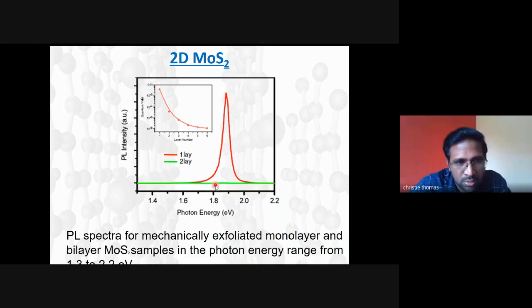Okay, and also in the inset, I think it's not clear. The y-axis is quantum yield, okay, versus the layer number. Layer number means number of layers of MoS2. So you can see that as the layer number decreases, the PL quantum yield, photoluminescence quantum yield, increases. Okay, so basically it has been seen that this indirect band gap MoS2 in bulk form is getting converted to direct band gap material when it is thinned down to 2D material. Okay, which is quite interesting.